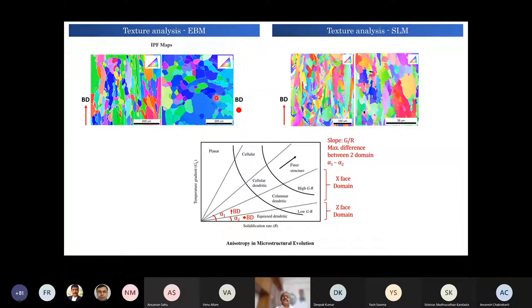But we could very clearly see the difference between EBM and SLM processes in the most optimized condition for 718. And we could tailor the desirable range for getting suitable microstructure, like equiaxed microstructures, which are very highly desirable for many room temperature properties. So this kind of microstructure has a special attribute of having a good combination of room temperature strength and ductility. So we could hit the condition by which we can get these parameters. And in other cases, we have other properties which are maximized or minimized.